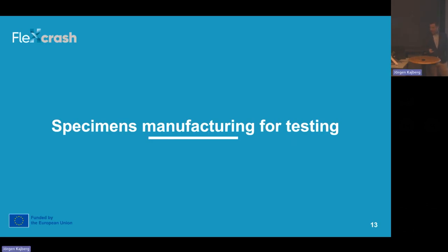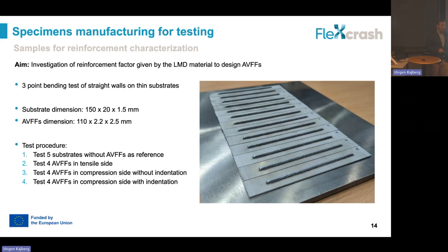So the last step, and what we are currently working on in the project, is the specimen manufacturing, as was presented in the presentation before, and the first trials that we are going to test to characterize the material we deposit. So now we used 1.5 millimeter thick substrates. And here, as you can imagine, it's really important, what I said at the beginning, to control the amount of material from the substrate that we remelt, and to avoid cutting or going through the thickness of the material. Our aim now is to try to test this material with a 3-point bending test.